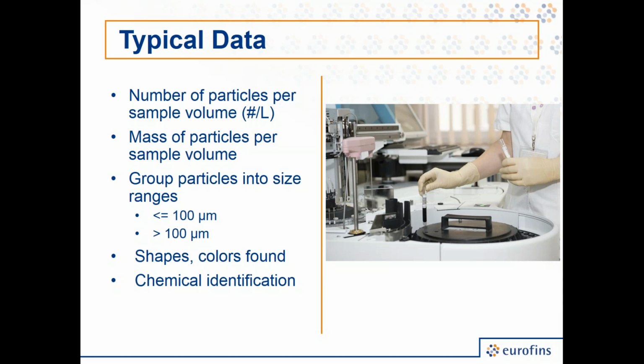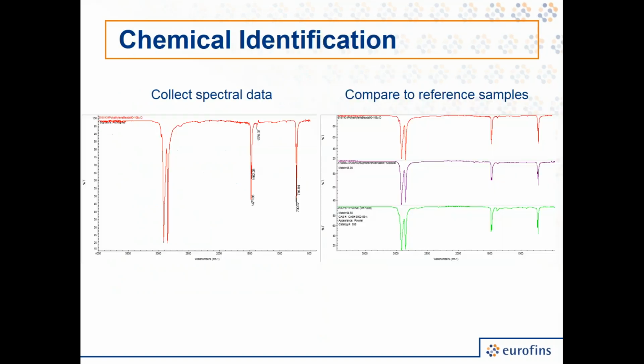Again, color sometimes is a very important piece of information. And if requested, we'll perform spectroscopy to determine chemical identification. So if we're doing this work manually, we typically have to work with particles that are much greater than 100 microns because we're manually pulling off these bigger pieces of plastic and transferring them to a benchtop FTIR to collect some spectral data. So, for example, from our sample, we may see a spectrum like this.